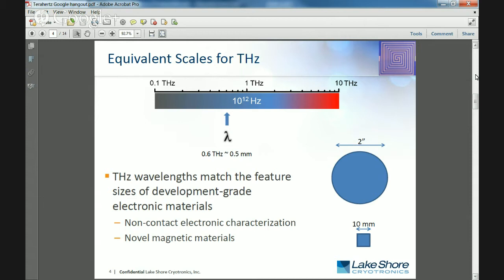This saves costs on substrate material, but if we're using the conventional characterization method, with that small sample, you're not going to get good results using these conventional techniques. And so what we've found is that by using terahertz, we can couple more efficiently to these smaller samples and allow non-contact evaluation for these research-grade materials.